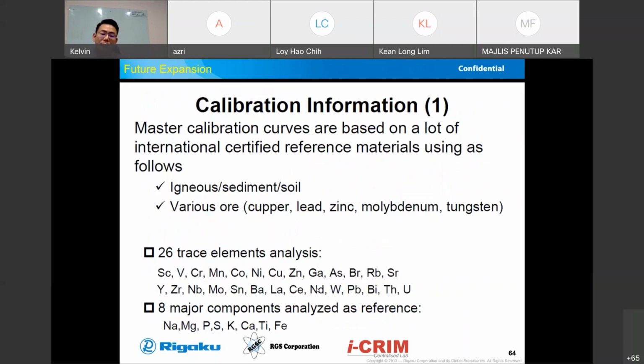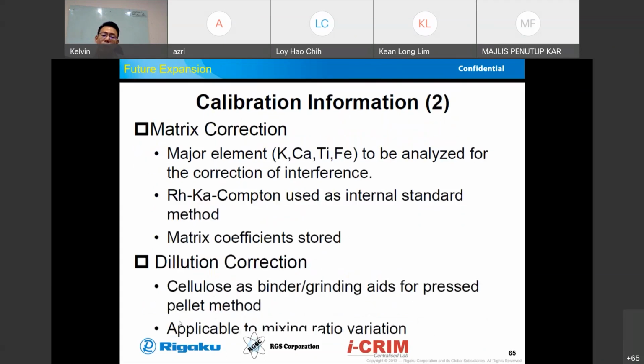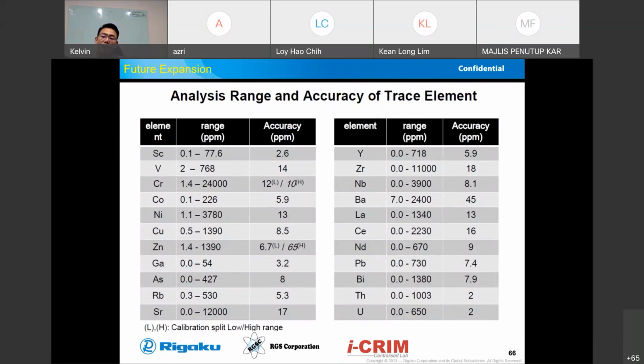So in the trace pack itself, this is the element content. We see quite a lot of customers who are very interested in the rare earth elements, La, Ce and the others. So this package covers this type of element, and the major elements can also be measured inside the sample. It then automatically corrects all the matrix corrections in this trace pack. And this is the analysis range for the trace elements. You can see that it is mainly very low concentration, because naturally the amount of these types of elements is very small.